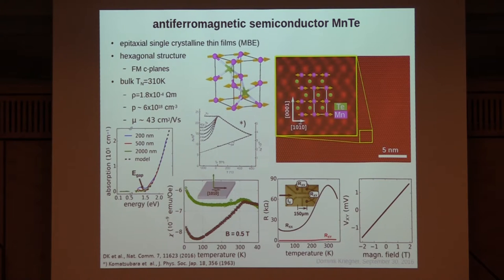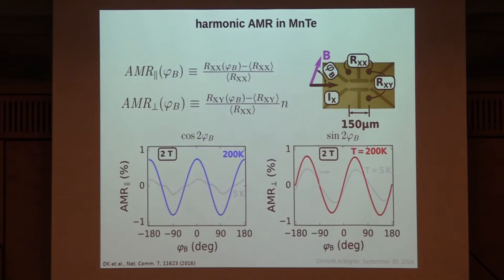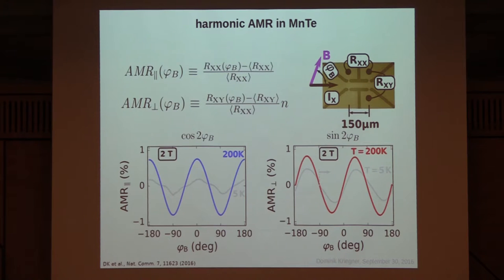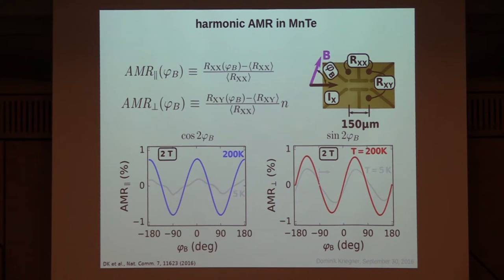When we apply a field to this material we expected rather low anisotropy and wanted to see if we can detect AMR. We went to 2 Tesla — the highest available — and rotated it in-plane using a lithographically patterned Hall bar, detecting longitudinal and transversal resistance changes. At 200 K, safely below the Néel temperature, we see harmonic AMR in complete analogy to ferromagnets. However, when we cool further, it becomes more complicated: we get different signals in transversal and longitudinal channels and higher-order terms appear.